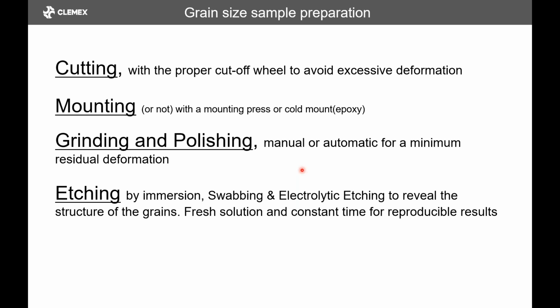Etching, of course, will reveal the grains, so there are various ways of doing this: immersion, swabbing, electrolytic etching. There are other ones. But to make sure that we're repeatable, what's important is that a fresh solution should be used and a constant time for reproducible results. So if your etchant has been there for 2 weeks, and then you leave your sample in it for a longer time, you might end up with a burned sample, and it's very difficult to get reproducible results. So if you make a habit of changing your solution every other day, and then you keep your etching time, then you should have consistent results.